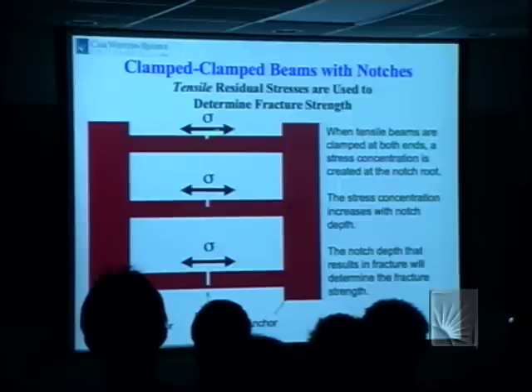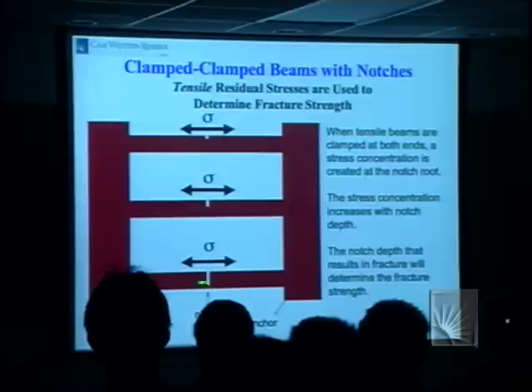MEMS types talk about a clamped beam. So this is a beam which is anchored here and here. And the way we did this, we built devices with varying micromachined notches. These don't have sharp notch tips. They're rounded, but nevertheless, there's stress concentrations. And the way the measurement works, we build a device. We actually have a dozen or so of these beams with different notch depths. And we look to see which beams have fractured and which haven't. Those beams in which the stress concentration times the residual stress at the root of the notch is larger than the fracture strength will fail, and the shorter notches will not.